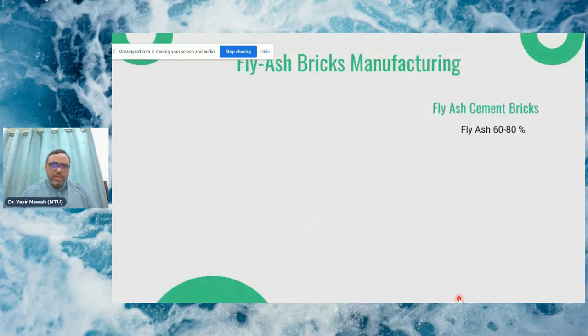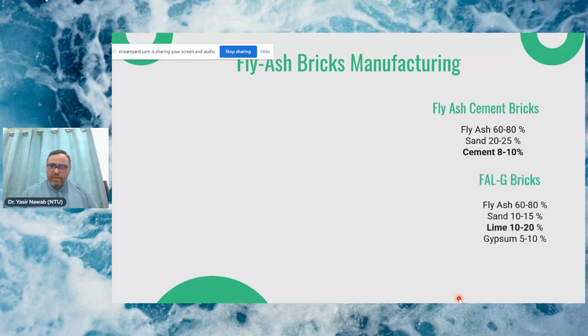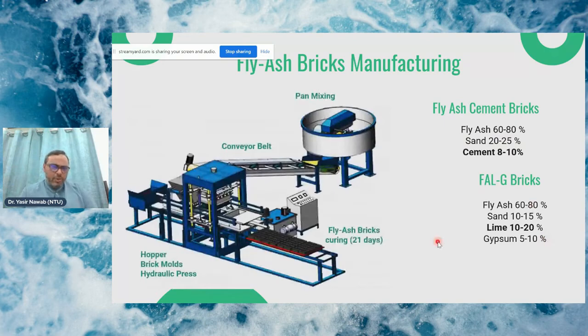So one of the applications is fly ash bricks. There are two possibilities: fly ash cement bricks, in which we use 8 to 10% of cement along with fly ash and sand, and the second one is fly ash, lime and gypsum bricks, where we use 10 to 20% of lime. The plant we use is a simple plant. We need a pan mixer where we mix all the constituents. Then it's conveyed to the brick mold, and after pressing, there is curing. In general, the curing takes 20 to 21 days.